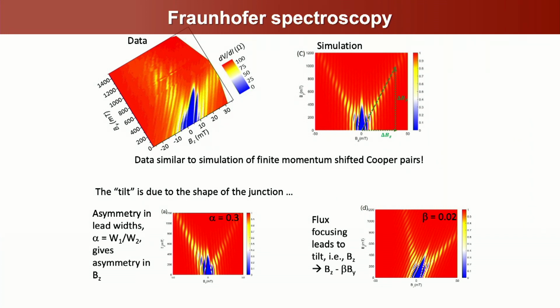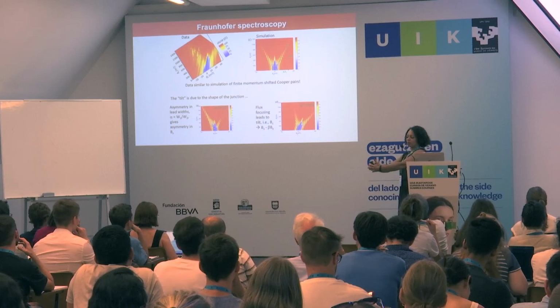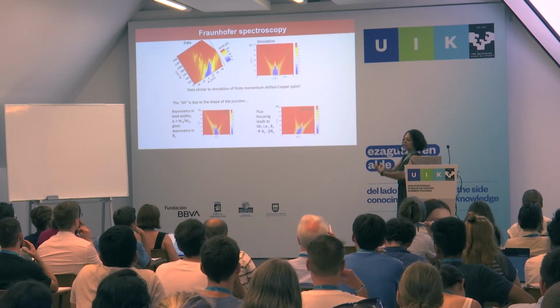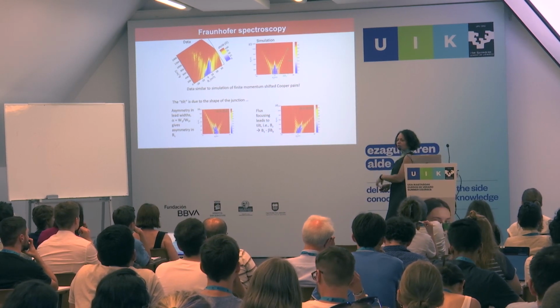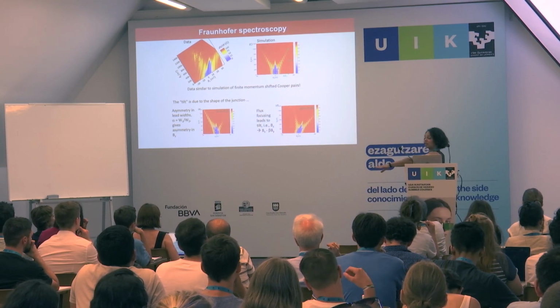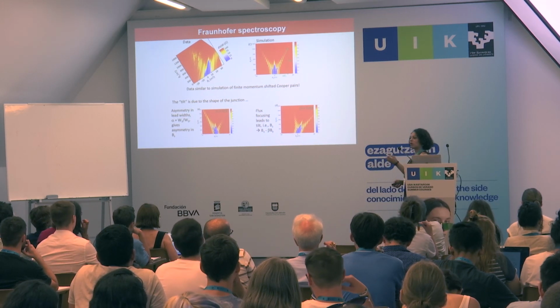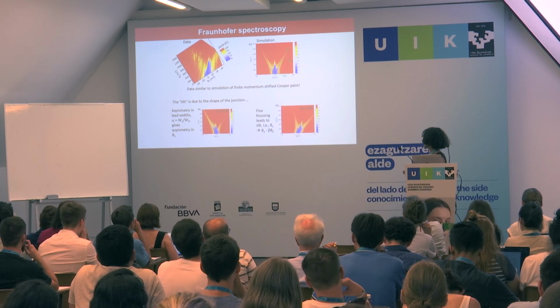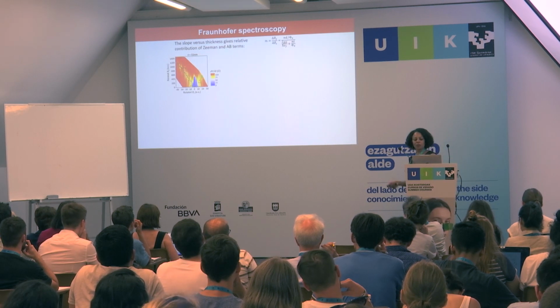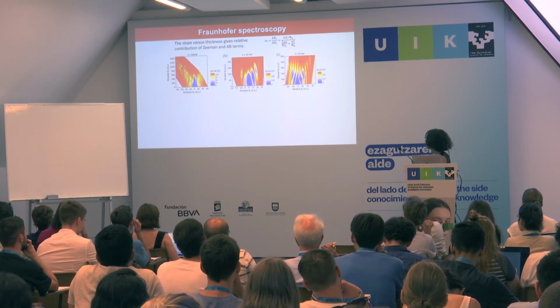Flux focusing is just if you apply an in-plane field, because of the Meissner effect of the leads, it basically creates a small component of out-of-plane field. And we apply a really strong in-plane field in a very small out-of-plane field. So a small amount of flux focusing leads to this sort of tilt in the data. But we can basically prove that we have the sort of patterns that we expect.